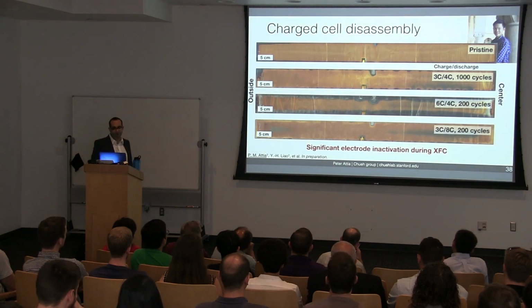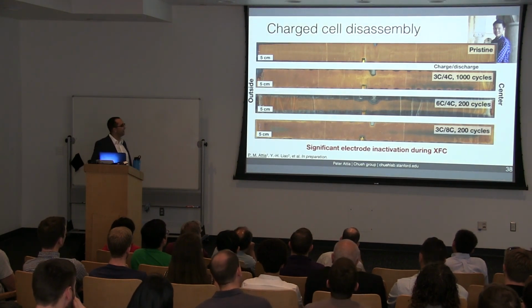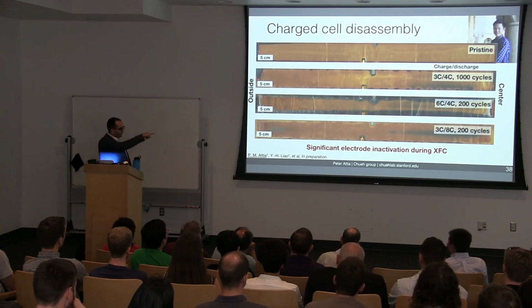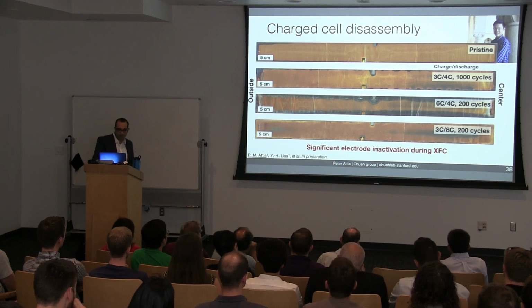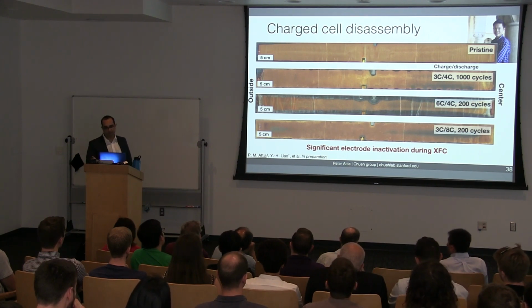And what's really interesting is if we look at a cell that was slow charged but fast discharged, we don't see this widespread degradation. We do see a little bit towards the center, in the middle, but it's much less than the fast charge cell. So our conclusion here is that significant electrode deactivation only occurs during extreme fast charging.